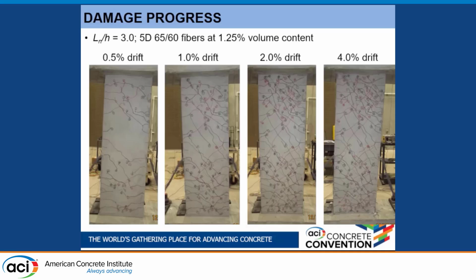Photos showing the damage progress up to 4% drift in this case. As you can see, beyond 2%, pretty much all the cracking had developed. As I mentioned earlier, because of the material we use, we got a fairly dense cracking distribution.